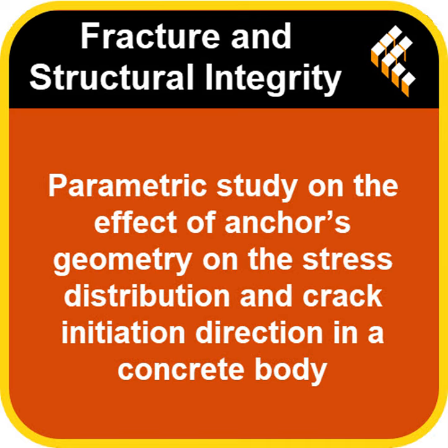Okay, so they've built their virtual test rig. What specific anchor shapes did they actually change and analyze? They focused on a couple of key things. First, the anchor's outer radius, labeled R2. They tested 6 values from 20 up to 40 millimeters. Okay, the width. Yep. Second was the embedment length, lem, basically how deep the anchor goes into the concrete. They looked at a really wide range here, from 50 millimeters, quite shallow, up to 500 millimeters, very deep. Half a meter, wow. Yeah.